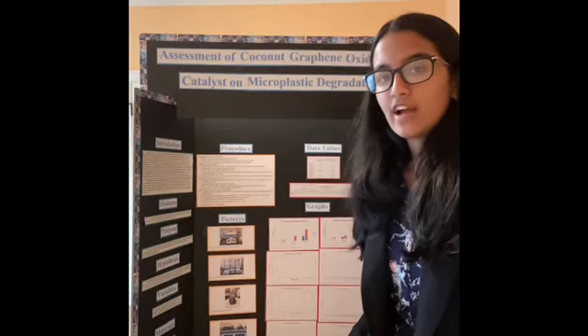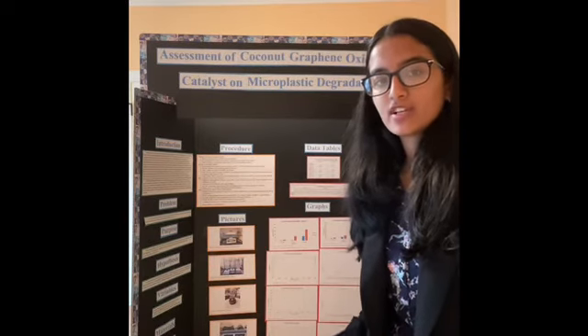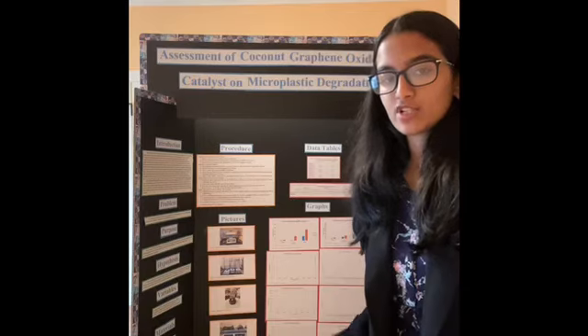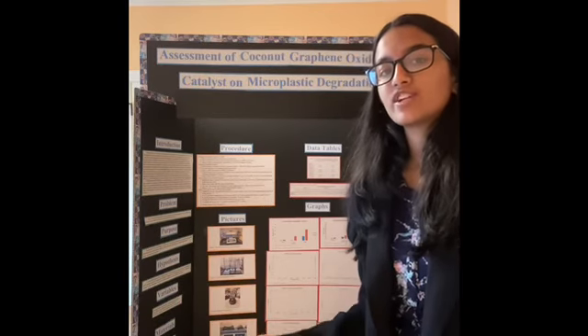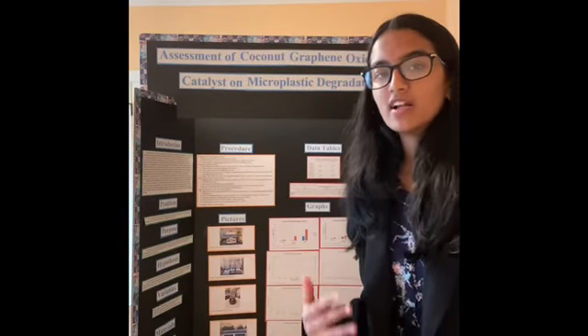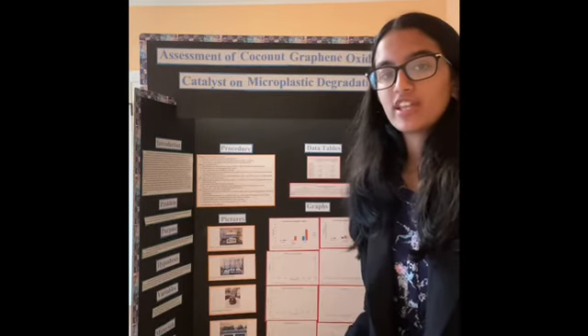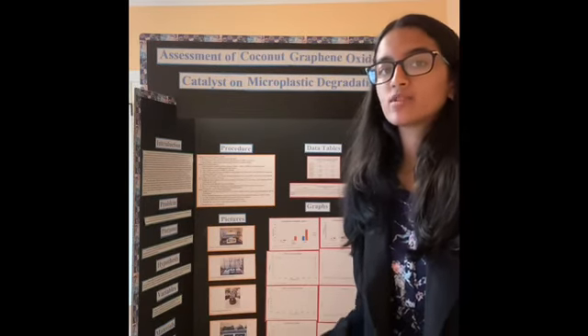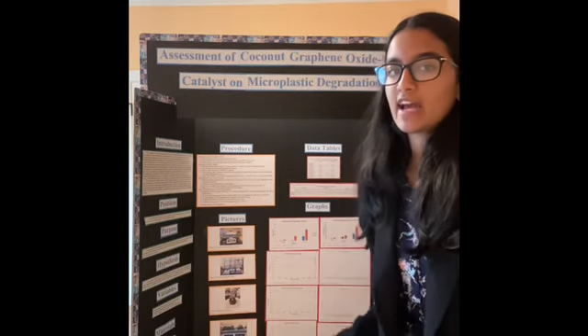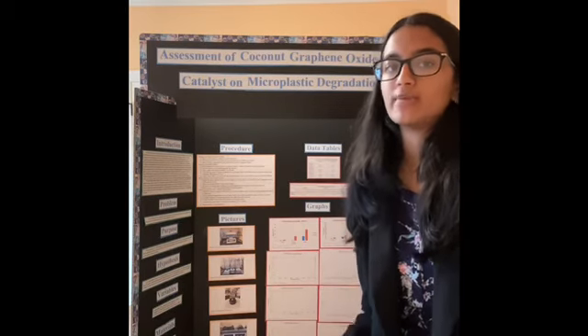With the XRD, I found that the coconut graphene oxide and the coconut charcoal were formed through the peaks that were shown in the XRD, and then for the XRD of the catalyst, I found that the coconut graphene oxide peak was shown and there was a slight manganese peak, but I would have to repeat this XRD for the catalyst to see if there was a more defined manganese peak.